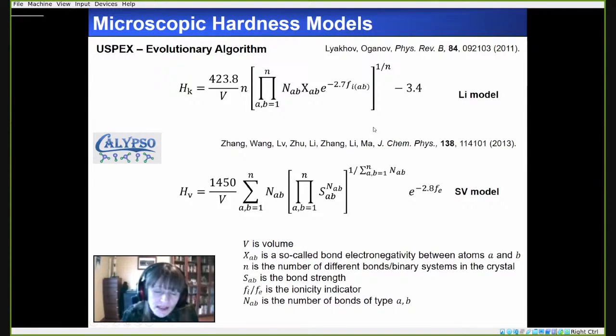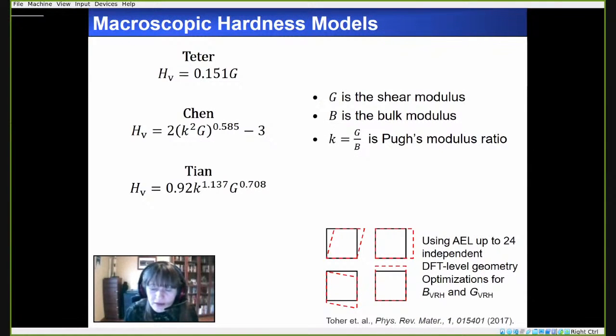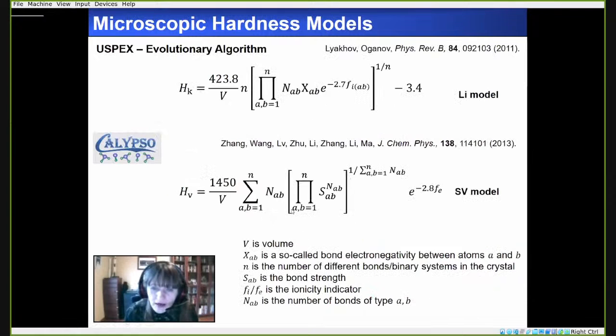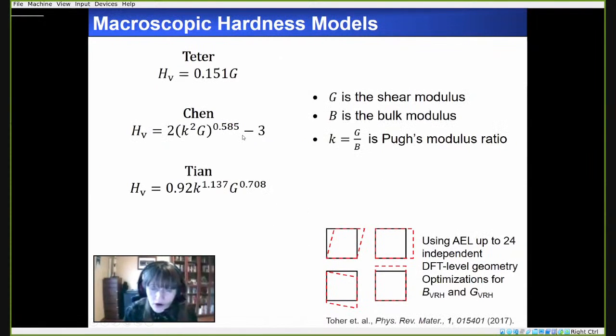And what they do is that they estimate the hardness of the material using micro-hardness models that basically depend upon the geometry of the crystals, and also on a number of different models which take into account, for example, the bond strength, the ionicity of the systems, and the number of bonds. Now, all of these types of quantities are estimated using some sort of formula. They're not calculated from first principles. And because of that, some of these parameters are quite difficult to estimate, even though the micro-hardness models are fast.